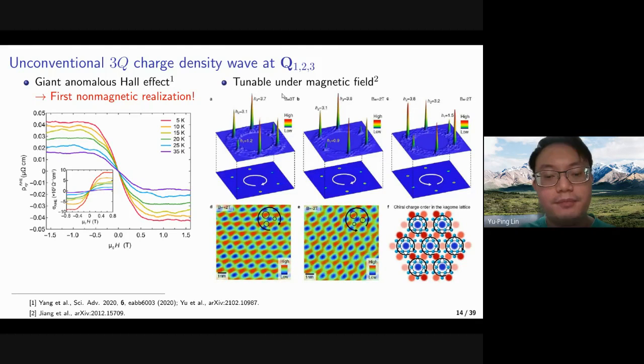Meanwhile, it was found near the end of last year that the charge order actually shows a density modulation in real space. And because some other measurements have shown the absence of the magnetic response, it is presumably a charge density wave. If we look at the scattering momentum spectrum, there are 3 peaks, which correspond to Q1, Q2, Q3 in between the saddle points. And we'll see that the peak heights are different at Q1, Q2, Q3.